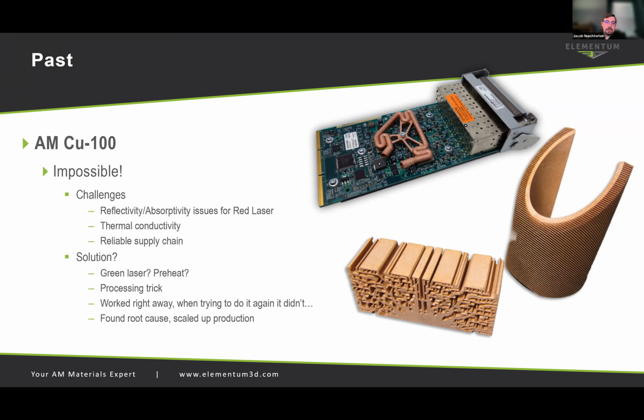So that's when we really started diving into, as it says here, a process in which we could produce the copper material with a coating on the powder itself. So we could actually start printing pure copper material with that coating that enhanced the absorptivity. So all of a sudden we could get to very high densities. We could get to full hermeticity, so that when you're doing something like a cooling channel for a complex chip such as this, or a heat exchanger or something along those lines, it doesn't leak, and the productivity was much higher.